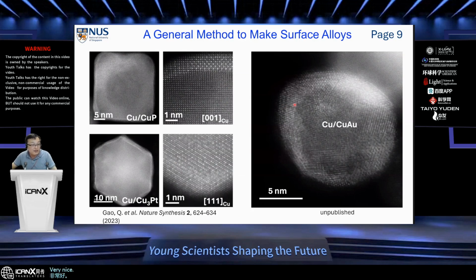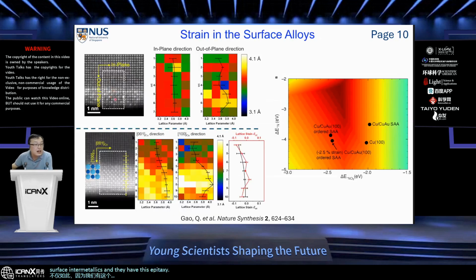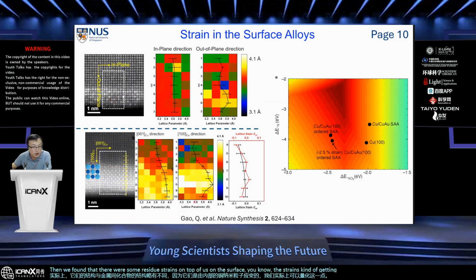Not only that, because we have these surface intermetallics, and they have this epitaxial structure, they actually have a slightly different structure than the bulk intermetallics, because they are sort of strained by the copper nanoparticle inside. And we can actually quantify this strain just by using high resolution imaging. Then we found that there were some residual strains on the surface. The strains are getting relaxed slightly, but you also always have a little bit left on the surface.